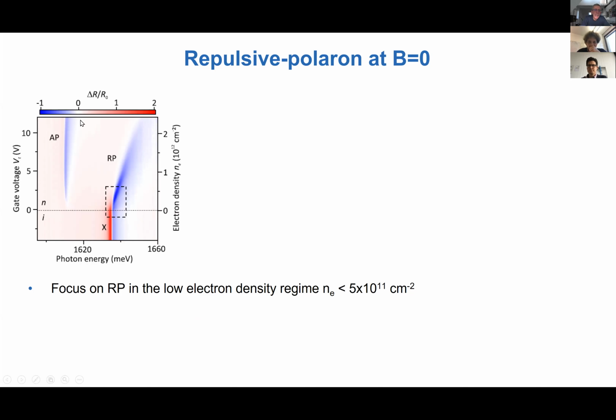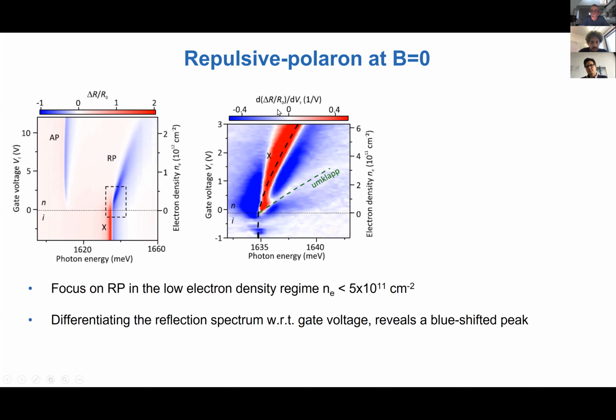So let's see what happens. This is yet another sample showing the repulsive polaron and attractive polaron at zero magnetic field as we dope the electron dome. So what we will do is focus on this region of low electron density, up to 5 times 10 to the 11. And we will also differentiate the signal with respect to voltage. And then we see that there is a peak that appears on the blue side of the exciton, and that shifts as we increase the electron density.